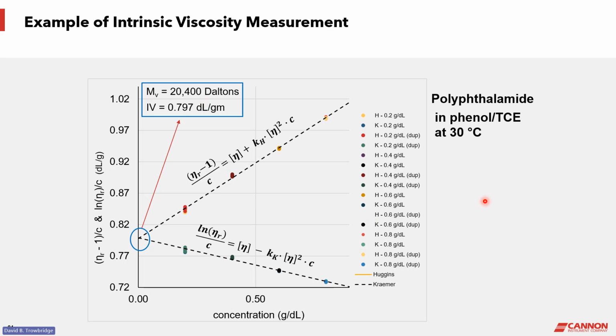And I can get that molecular weight because I've used the Mark-Houwink equation in the form that gives us an opportunity to calculate molecular weight. I have the measured intrinsic viscosity, and the K and a values I got from the Polymer Handbook, which you may be able to see here in my stack of books. The first 2 large blue ones are the Polymer Handbook, and they have a very, very extensive collection of K and a values for many polymer solvent systems.